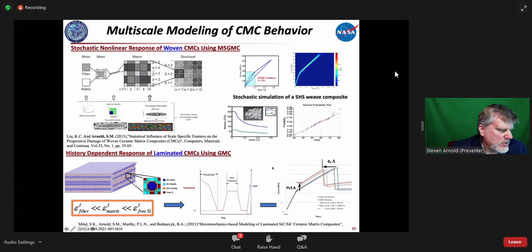And the residual stress that results, you can see its influence here is to move up the initial failure, or what we call PLS of the composite, and that's at the sacrifice of the total strain to failure. And obviously, depending upon the type of heat treatment that is done, you can minimize, or reduce, I should say, that effect of the residual stress due to manufacturing.